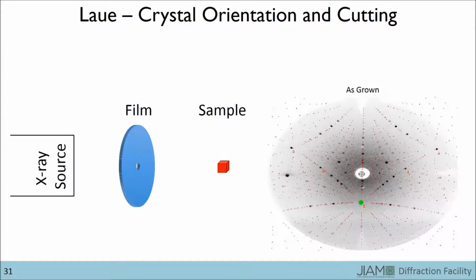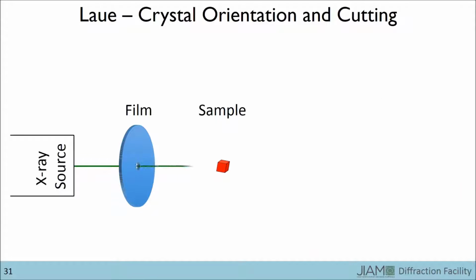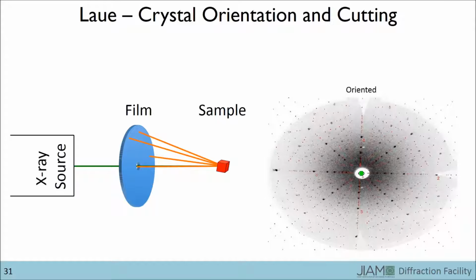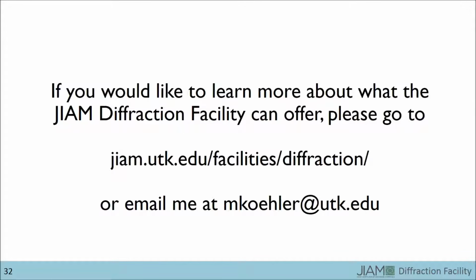Using our goniometers, I rotated the sample, ran another test, and found that the 100 plane was now in the center of the pattern, which means that it is perpendicular to the X-ray beam. I then cut the sample so that the new face would correspond to the 100 plane. Additional experiments could be performed to cut more faces to correspond to whichever planes are desired. That brings us to the end of the video.